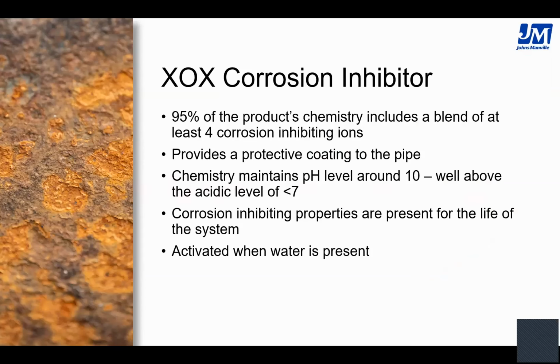Getting back to that corrosion inhibitor, our corrosion inhibitor is called XOX. You see quite often today that pipes are painted or coated before insulation is applied. One of the reasons folks do that is to keep moisture off the surface of the pipe. When moisture contacts the surface is when you can have corrosion happen. The XOX actually provides a protective coating to the pipe, similar to and performing the same way as painting the pipe or putting some other coating on it. But this is contained in the material itself. 95% of our chemistry includes a blend of at least 4 different corrosion inhibiting ions. It keeps the pH level around 10, and that's well above the acidic level below 7 where corrosion can occur.